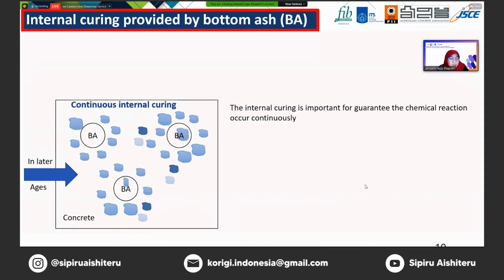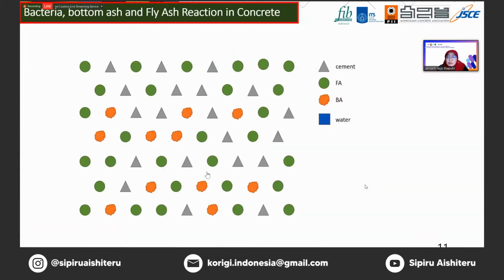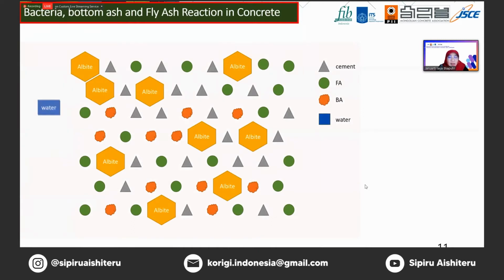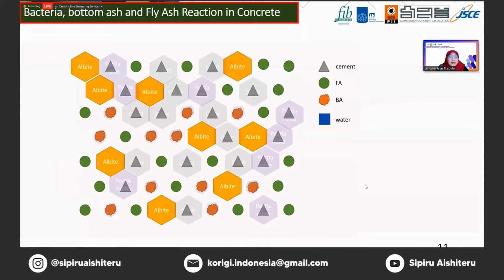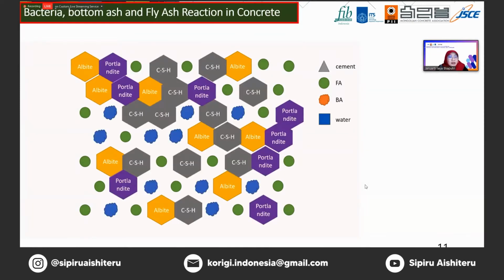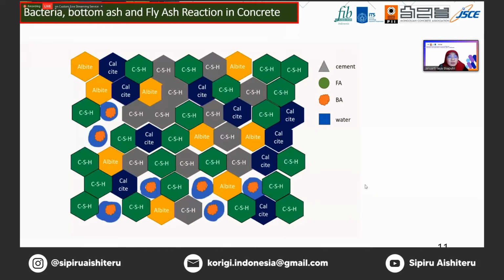bacterial activity. This is a bit complicated, but I tried my best to make simulations. This is the schematic reactions during the first hydrations and at the later age of the concrete using bacteria, bottom ash, and the fly ash. The bacteria produce CO2, which reacts with the portlandite to produce calcite, and the fly ash reacts with the portlandite to produce new calcium silicate hydrate. At the end, we have a denser concrete, and the bottom ash still works to guarantee the internal curing inside the concrete during the hardening process.